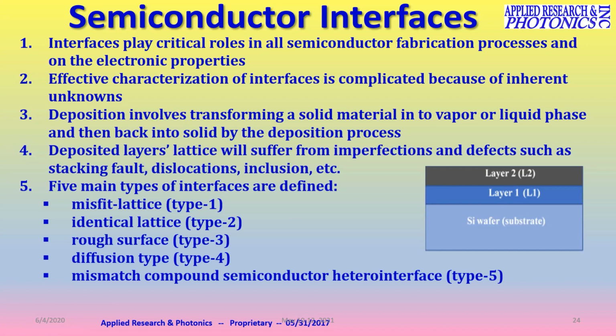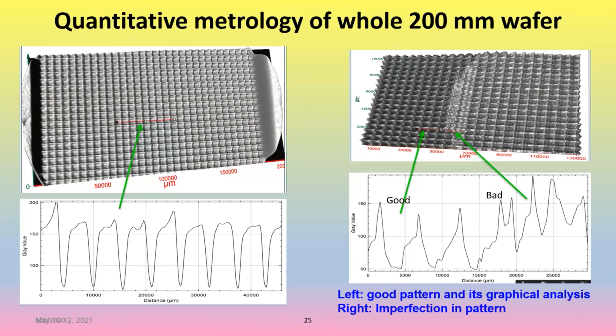So as you can see, the problem is that this is thick, on a wafer, you have layer, etc. So without breaking it, how do we see below that if the interface is good or bad, or if the process needs to be adjusted so that this interface is perfect the way it should be? Because if the interface has delamination or contamination or inclusion or that kind of defects, it will not function properly.